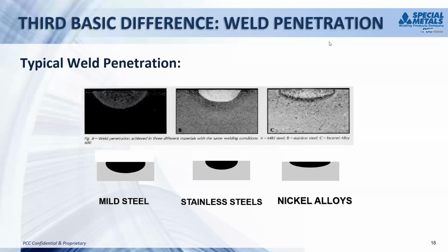The top row of pictures up there are actual cross sections of materials that these welds were made autogenously on: steel on the far left, stainless steel in the middle, and Inconel 600 on the far right. And if you notice, these were all made at the same amperage, voltage, and travel speed and so forth, same size plates and so forth. But because of the nature of the materials, the penetration is quite different, as you can see.